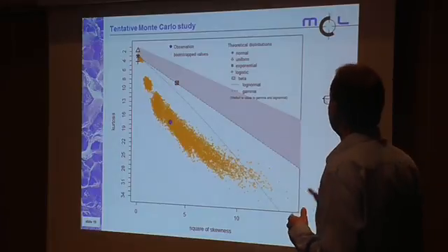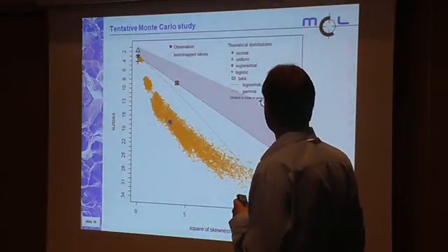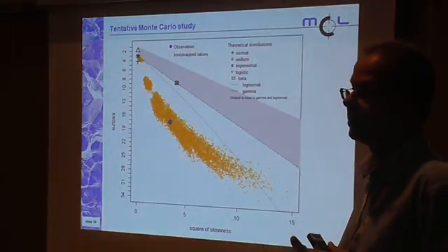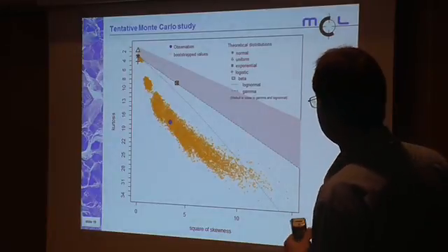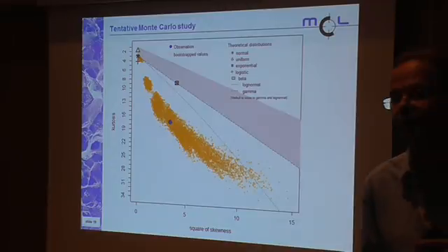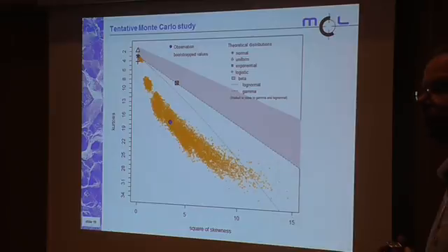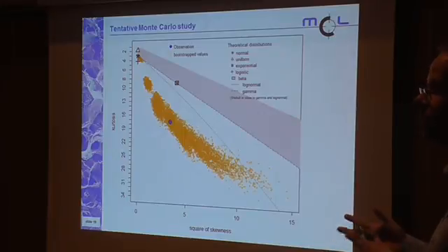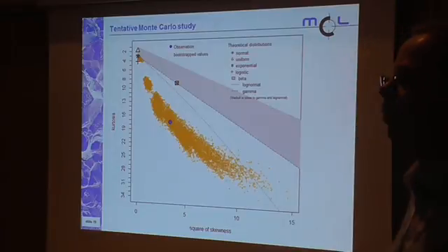Of course, we also see, regarding the orange data points, which is scattered from the bootstrap samples, we see that lots more simulations will be necessary to get the real empirical distribution. But anyway, the message is, as we feel at the moment, the lifetime, at least the fatigue crack growth lifetime, cannot be approximated by any of the simple statistical distributions. We will have to do some more simulations to get the real empirical distribution as from simulations. But for sure, the classical assumptions as to being normal or a log normal distributions are probably not completely correct. Albeit is the best what we can do regarding the small number of tests that we normally have.